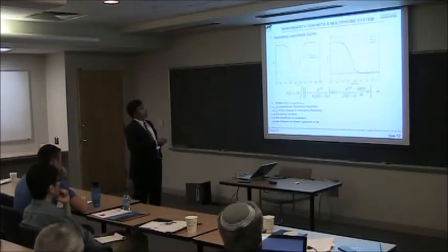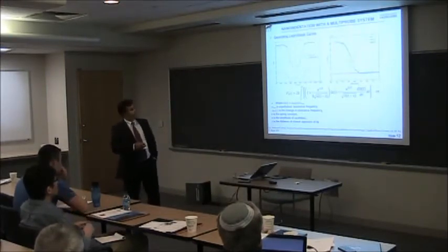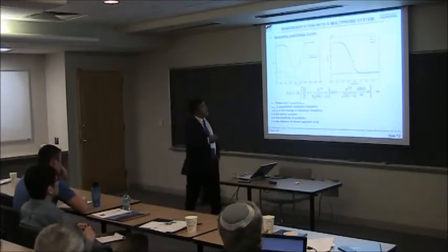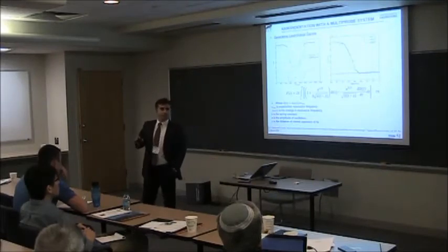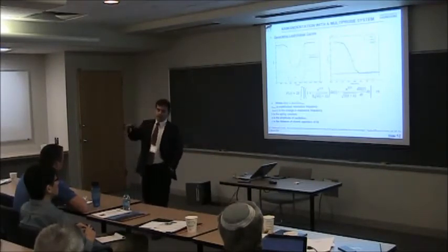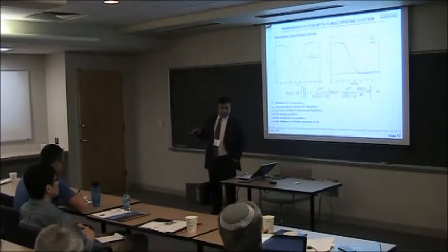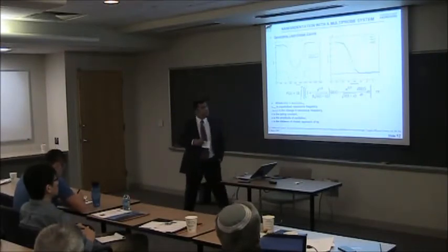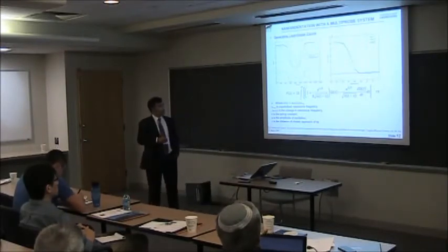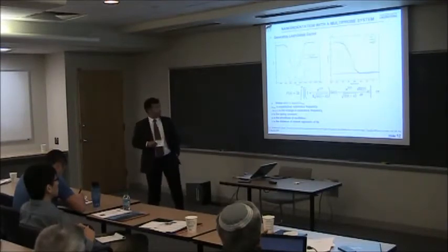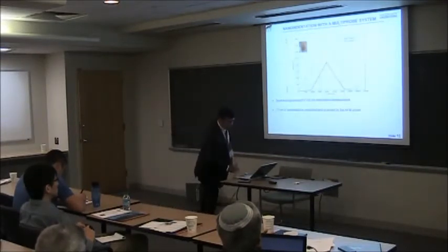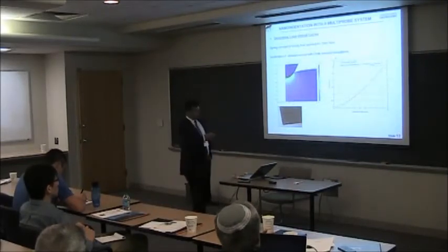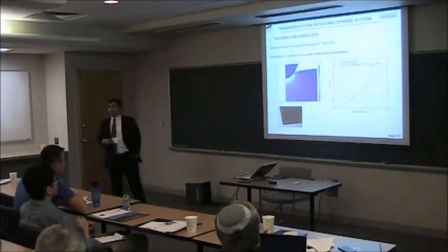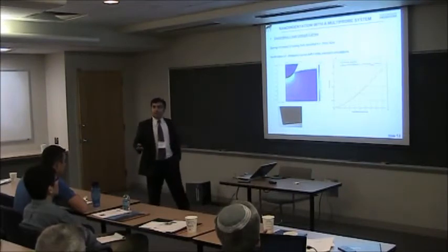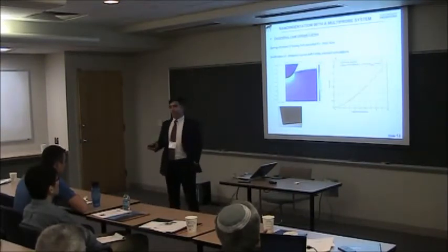And this is our load-unload curve for the silicon. And if you look at the values, they are at the 100 micronewton level, which is good in terms of literature reported values. And there was only a small thing that we had to do regarding this formulation. The K, in fact, K is generally 2600. The Nanonics is actually reporting right there. So we said, well, this is saying it's 100 micronewton, but is it really 100 micronewton? How do I verify that?